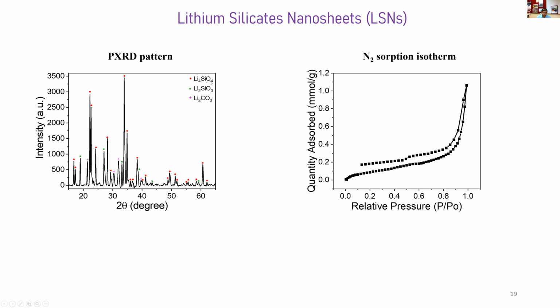But we decided not to use the inert atmosphere because then again the process will become less sustainable. We said, okay, it's okay to have some amount of impurity if I'm still able to get a good amount of CO2 capture using, say, a 90% pure material. Surface area was no good, but here it's more a reaction. It's more a molecular reaction of Li4SiO4 with the CO2. So surface area should not matter much.